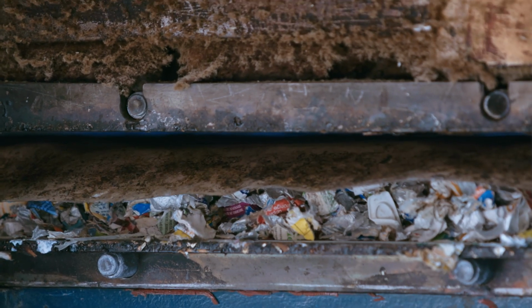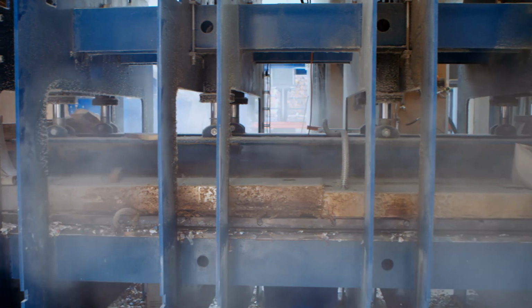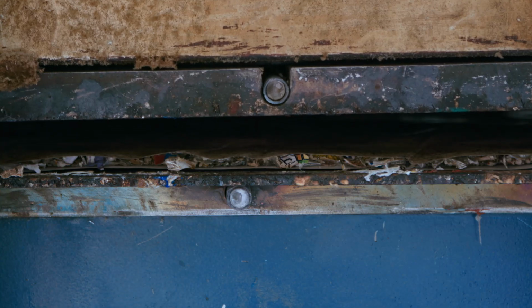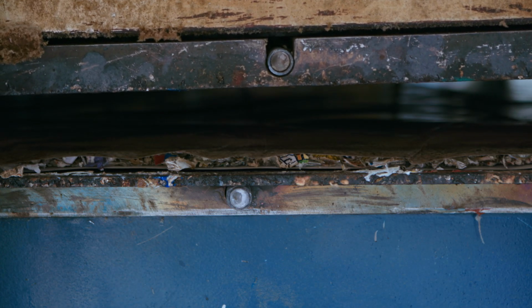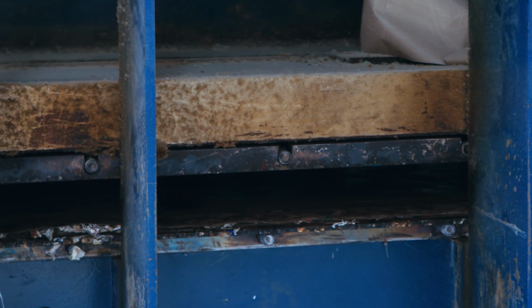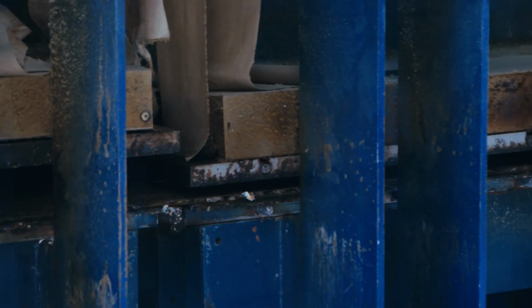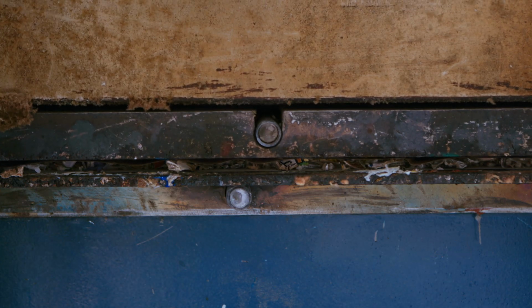The first press densifies the material, packing it down from 12 centimeters to 2 centimeters thick. Steam melts the polyethylene, which acts like hot wax to meld the paper and aluminum chips together into a composite sheet. Another press blows cool air onto the sheet to chill and set the wax, which solidifies it into a stiff composite board.